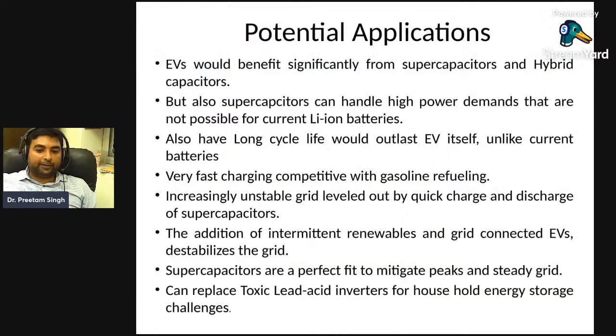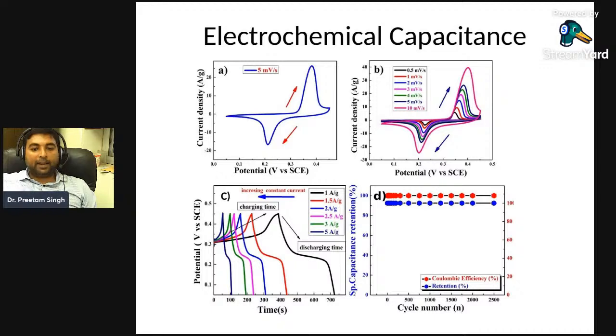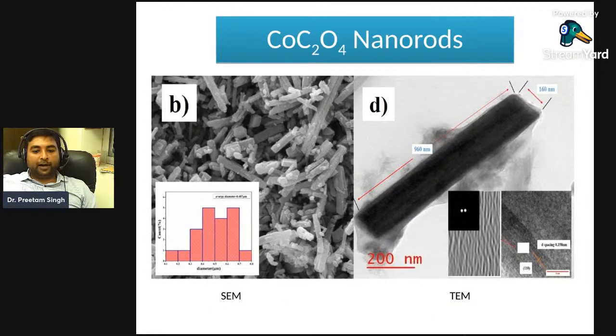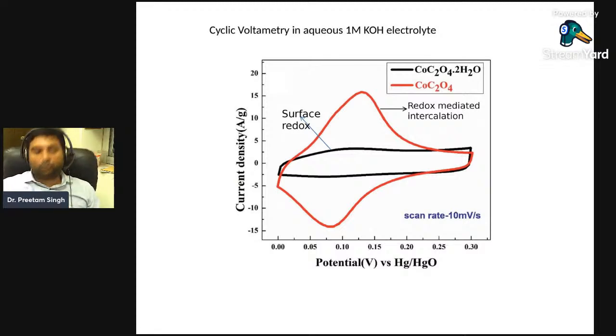No, that's what we have not found. See, the performance is actually very stable, and that's why we had the doubt when we remove this water, because we do this very slow step coupled with the TGA experiment. When we looked at the phase transformation with that very slow water removal, what we feel is that the oxalate rotation is actually working, and we are getting a three-dimensional stable structure. So it actually intercalates the hydroxide, but it doesn't take water back into the structure. Otherwise it would act like a water storage material rather than an electrocatalytically active material. So we are not getting hydration of the anhydrous cobalt oxalate back into the hydrated material.